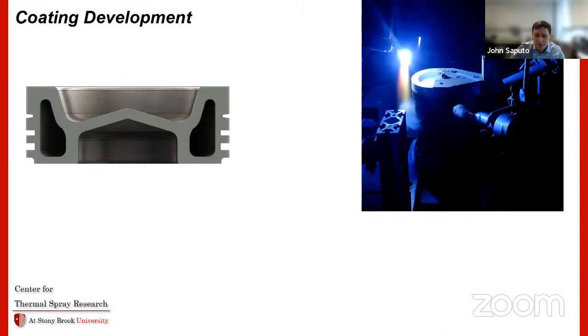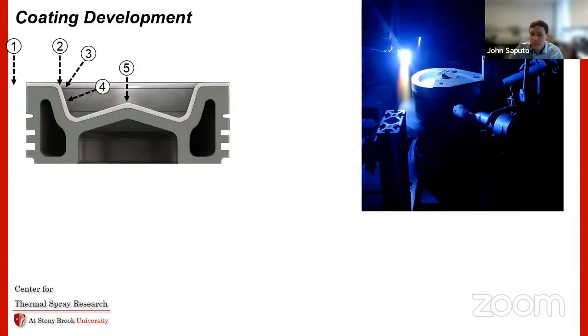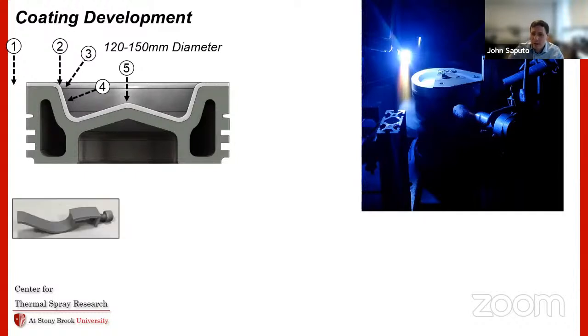So these generally look like something like this. You want to move a spray torch across this surface, keeping it normal the entire time in order to develop a uniform coating across the surface. So these pistons are something like 120 to 150 millimeters in diameter.